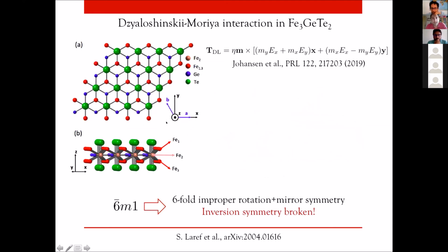What Arne Brataas and his students have shown is that you can get some very interesting current-driven anisotropy, which is essentially a damping torque. Well, let's call it a damping torque because it's even in magnetization. But you can actually get a torque with these very peculiar, very strange symmetries. What is interesting is that in the long-range limit, the damping torque and the Dzyaloshinskii-Moriya interaction have the same symmetries, in the long-range limit only.